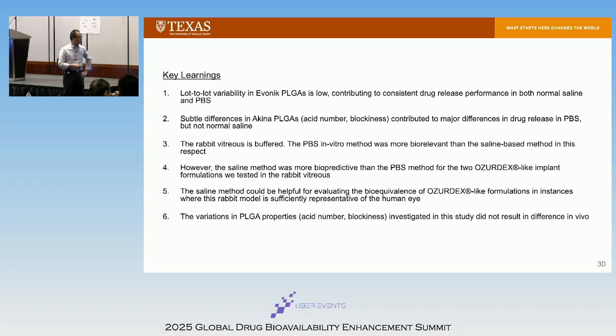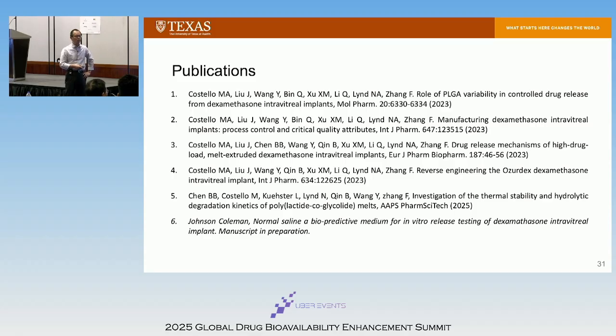So here are the key learnings. I'm not going to read all these details here, okay? But all our studies have been published. Early on, we did a study to understand the degradation kinetics of PLGA during the processing. It's about a 10% drop in the molecular weight. But the way we made implants, the material is in the extruder for 40 minutes. This is totally new learning for me as well because I used to do ASD, material flying out in 30 seconds, right? But this is very different, dimension controls the residence time, which is very long.